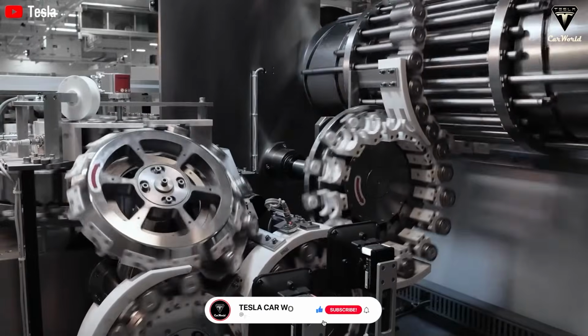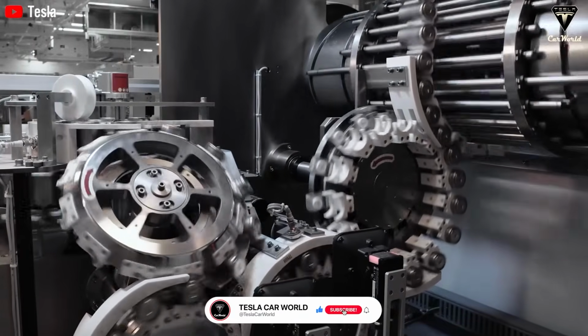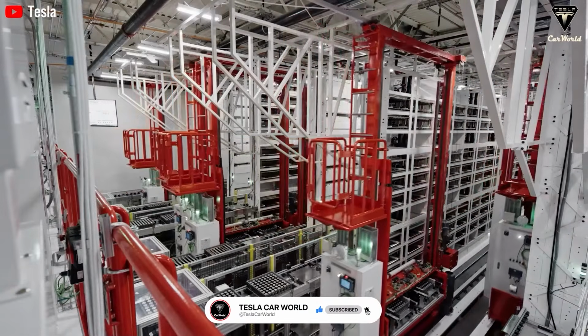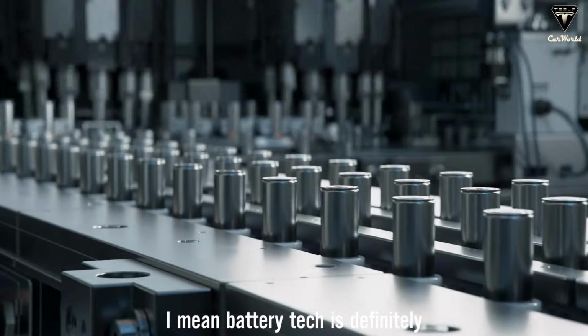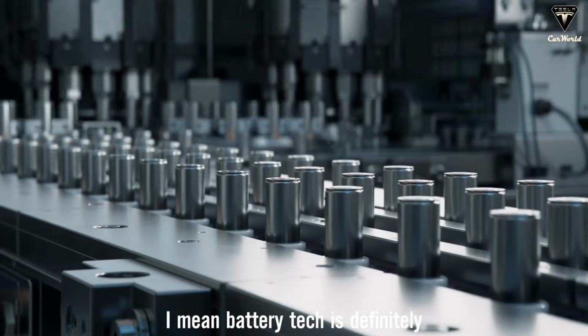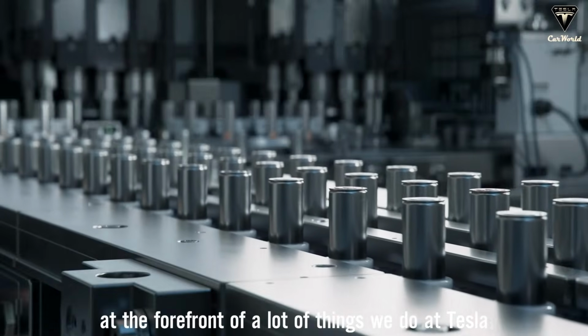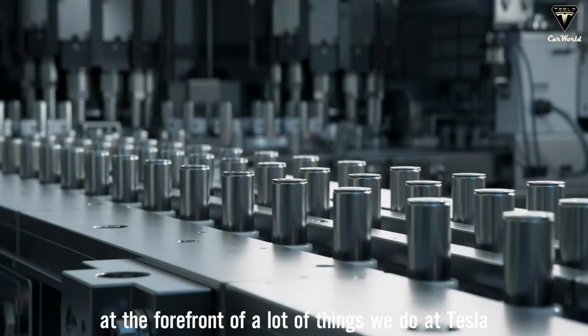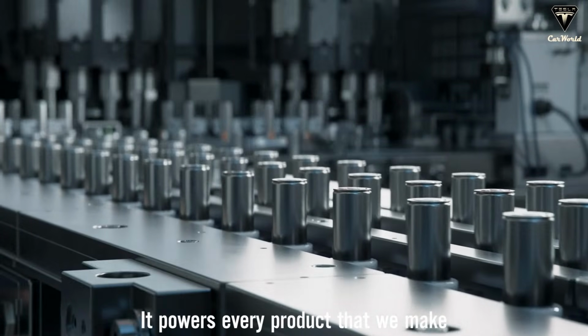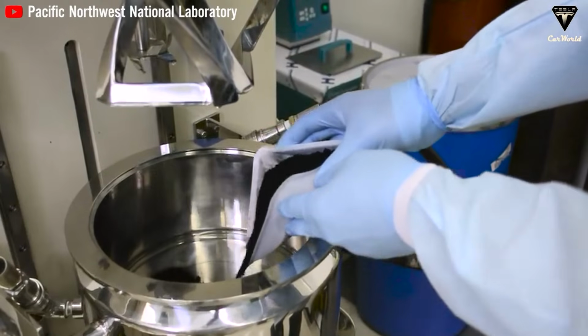Yet during this test, the Donut Lab battery continued to operate. The cell was discharged again, and the measured capacity reached 27.6 amp-hours, still higher than the room temperature reference measurement. However, one important detail was noticed after the 100 degrees Celsius test. The battery pouch had lost its vacuum seal.